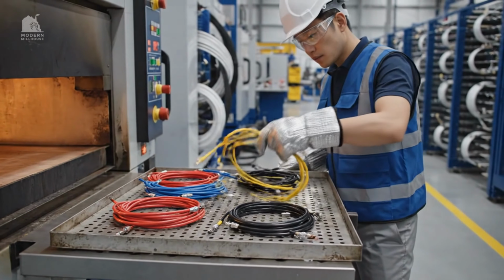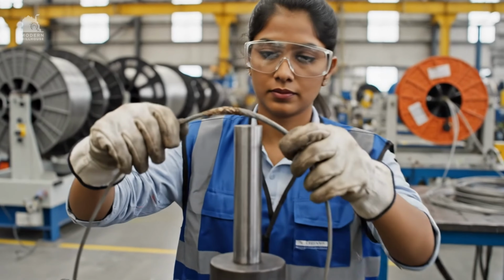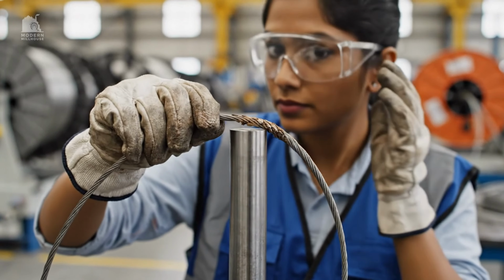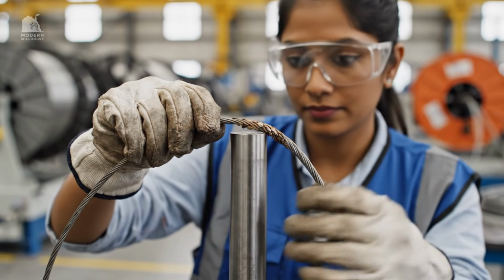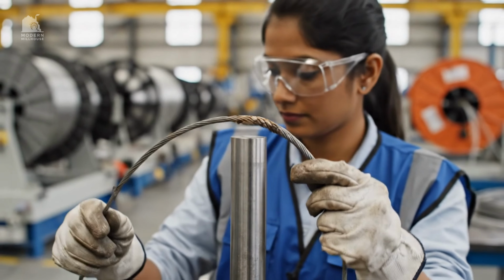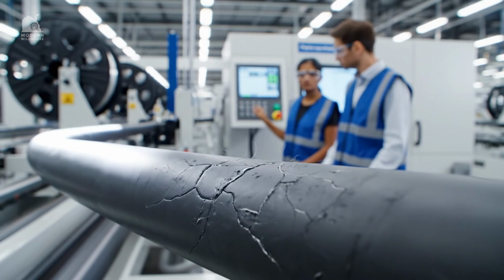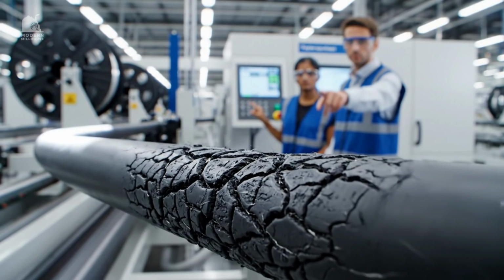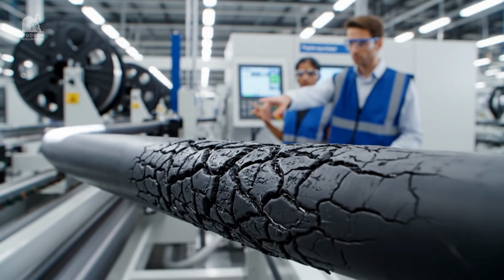After aging, the real question is hidden. Has flexibility dropped? And has strength degraded? Bending after heat can reveal micro cracks that aren't visible until the insulation is stressed. Aged cracking indicates the compound or extrusion conditions were wrong, and that batch can't ship.